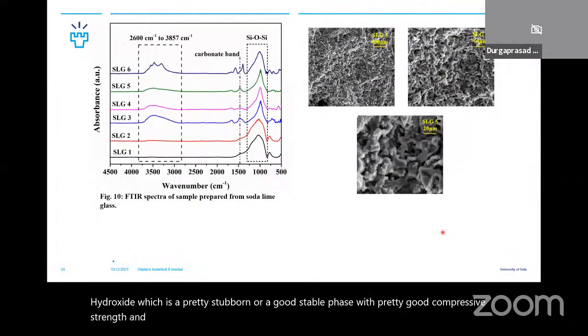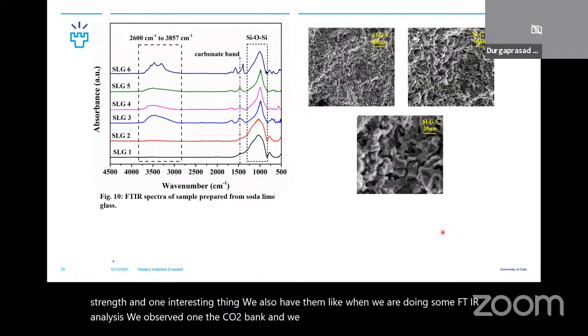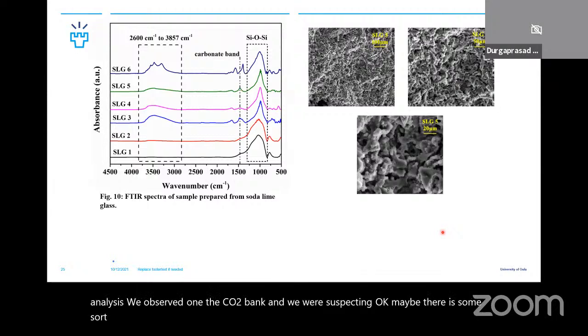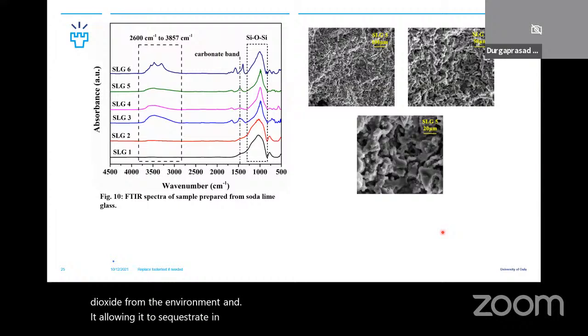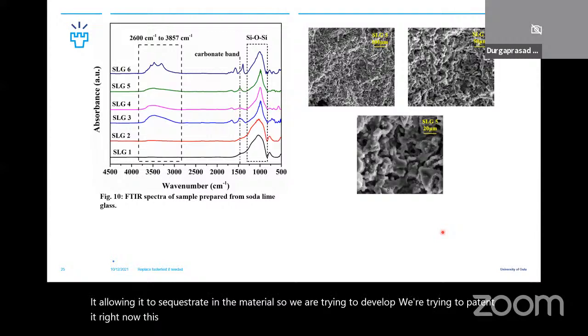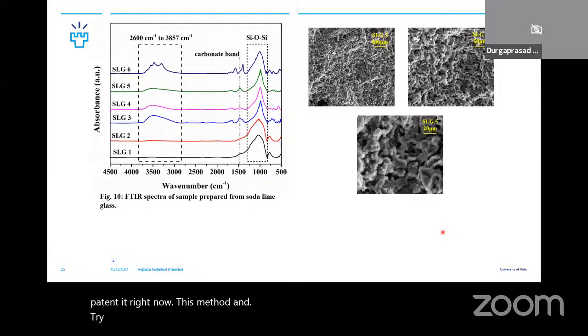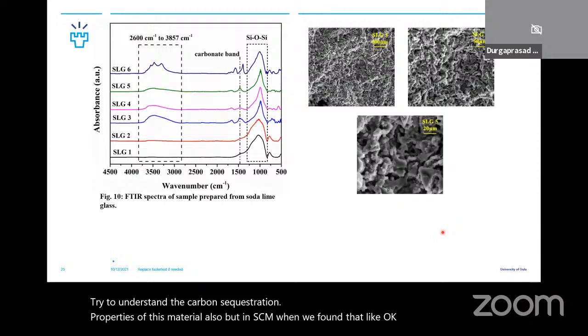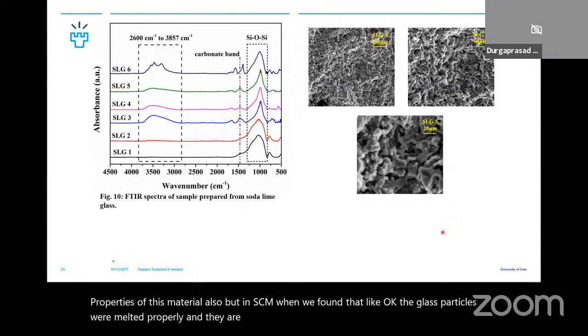One interesting thing we also observed, when doing some FTIR analysis, was a CO2 band. We suspected there may be some sort of carbon sequestration, where the material is absorbing carbon dioxide from the environment and allowing it to be sequestered in the material. We are trying to patent this method right now, and to understand the carbon sequestration properties of this material also. In SEM, we found that the glass particles were melted properly and are interconnected with some sort of micro pores.